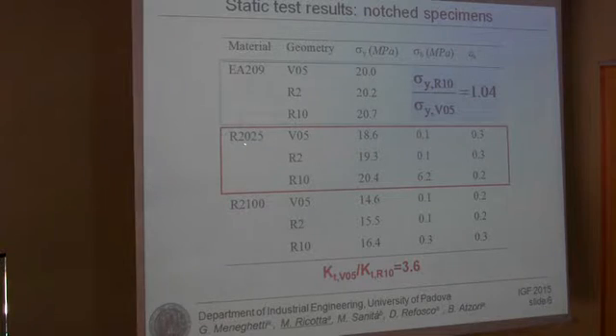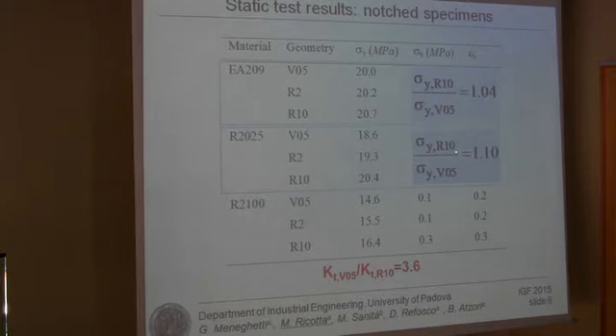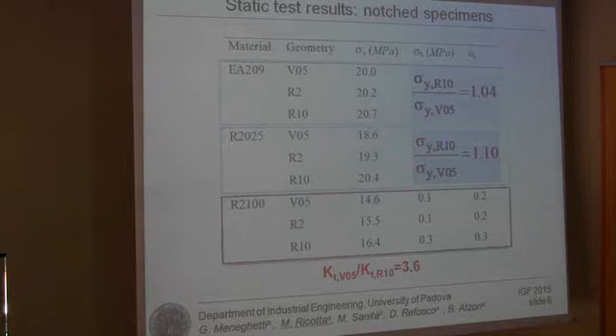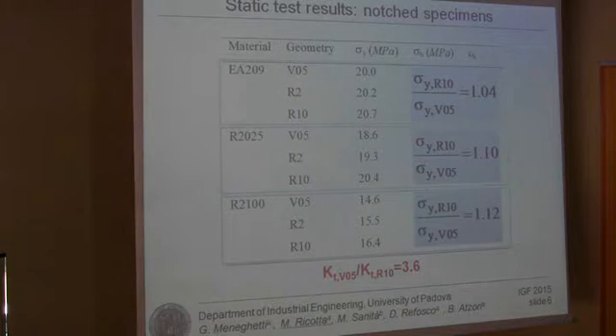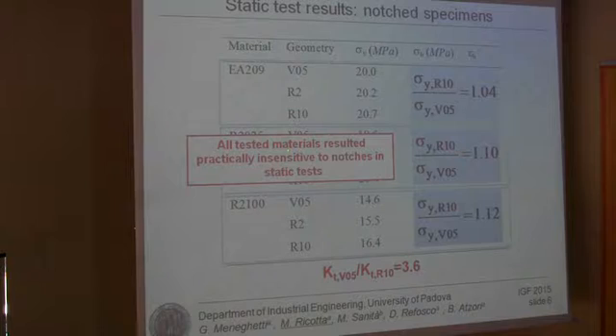Similar results were found also in the case of R2025 material, that means having 25% of recycled polypropylene, and we can see that the same ratio is equal to 1.1. And also in the case of totally recycled polypropylene, the ratio was equal to 1.12. Therefore, all tested materials resulted practically insensitive to notches in the case of static tests.